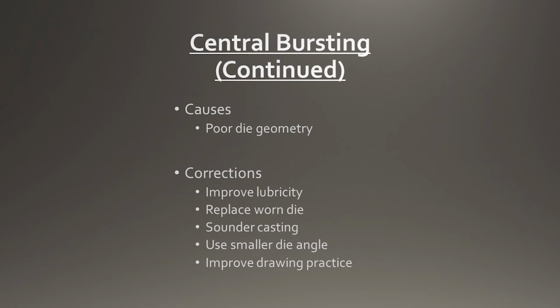Now, central bursting is usually caused by poor die geometry. That means too small a reduction in area, or too large a die angle. But look at the corrections. Improved lubricity, that's a drawing related issue. Well, replace a worn die makes sense. If it's worn too much, you might be getting a smaller reduction in area.